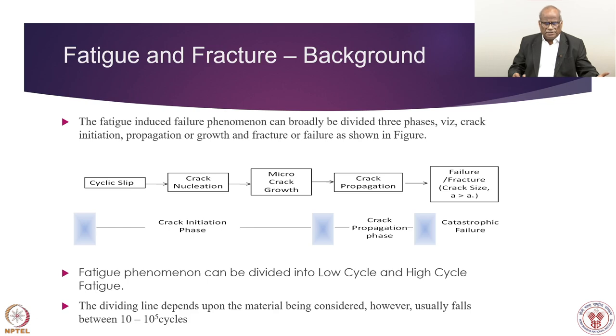Now let us see the background or preliminary introduction to fracture. Fracture has three main stages: one is crack initiation, second is crack propagation, and then catastrophic failure. At the root of it are cyclic slips. Once they accumulate, they form nucleation, and then micro cracks develop. These are phenomena systematically observed in cracks through experiments. And then the crack propagation and the fracture. That means when the crack reaches a critical size, where small a is bigger than a critical, then the catastrophic failure occurs. So this is how simplistically we can look at it.